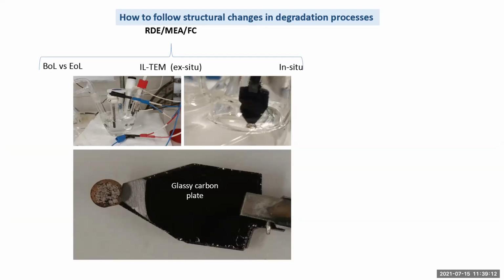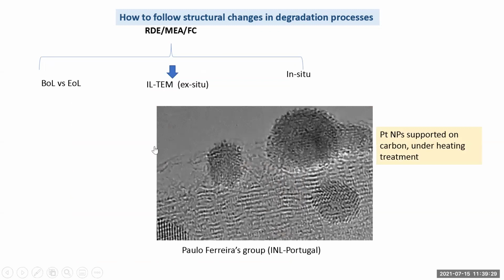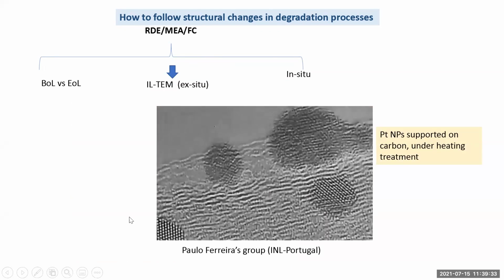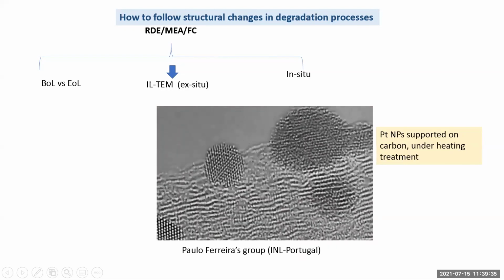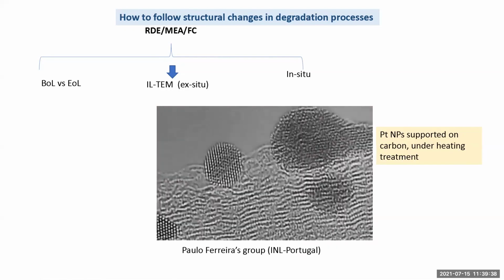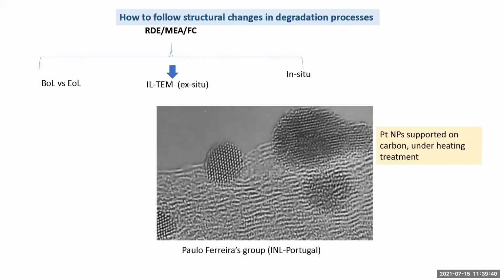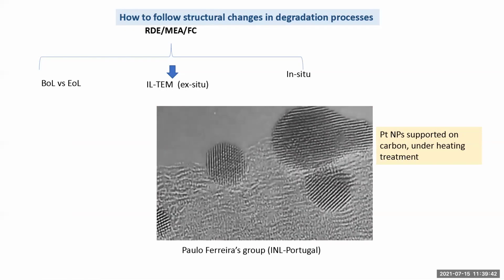We use specific grids for TEM, and then we cycle everything there. So all the electrochemical information that we take from this identical location is exactly the same as when we perform it on the electrodes. And this is the least used, but provides more information. That is our collaboration with the group of Paulo Ferreira. You can follow inside the microscope the structure and the change, and you can see even smaller changes.